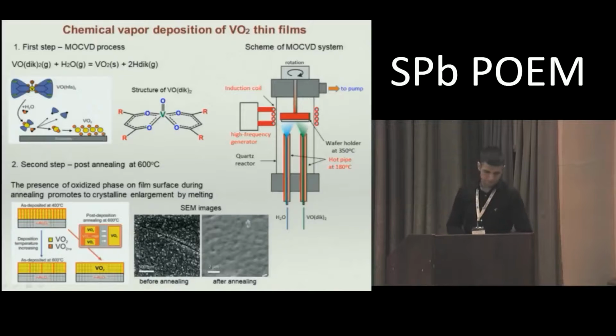We did it by chemical vapor deposition in a few steps. The first step was MOCVD deposition. We used complex substances of vanadium in oxidation state 4+, and steam of moist argon. As a result of the pyrohydrolytic reaction on the hot wafer, we have a thin film of pure vanadium dioxide. This reaction is shown here, and the structure of our complex substances is shown here.